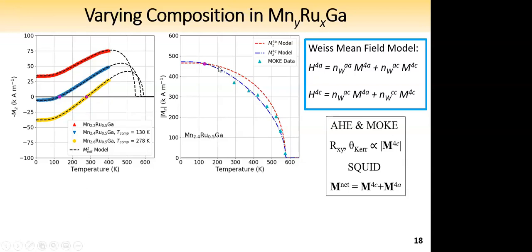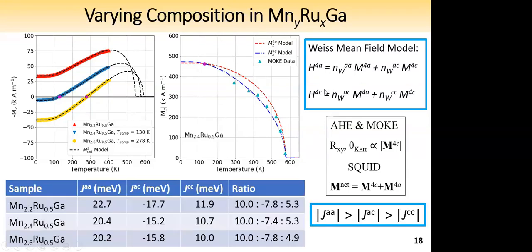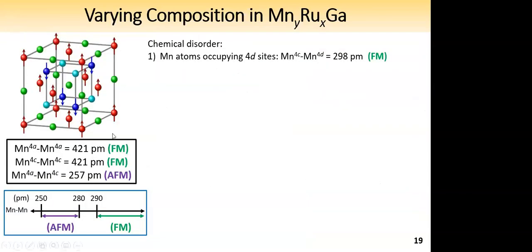So from these fittings, I can extract these Weiss constants and convert them into Heisenberg exchange energies. And they are summarized in the table. What we find is that JAA and JCC, so the intra-sublattice couplings, are positive, meaning they are ferromagnetic as we expected. JAC, the inter-sublattice coupling, is negative, indicating antiferromagnetic coupling. The hierarchy of the exchange constants is that the magnitude of JAA is larger than JAC, which is larger than JCC. So the exchange parameters depend on manganese-manganese distances in the unit cell. And in the next slide, the manganese-manganese distances will be shown for an ideal MRG case, as well as for MRG with a different stoichiometry with 2 types of disorder that can occur. So here I'm showing the unit cell again.